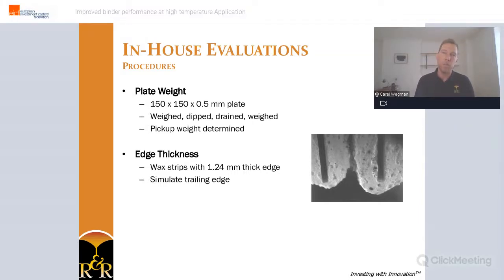The other two tests that we performed were plate weight and the edge thickness. The plate weight measurement evaluates the slurry pickup ability. Ideally, the more the slurry gets picked up for each dip, the thicker the shell becomes. A square plate of polished brass was used for this test.